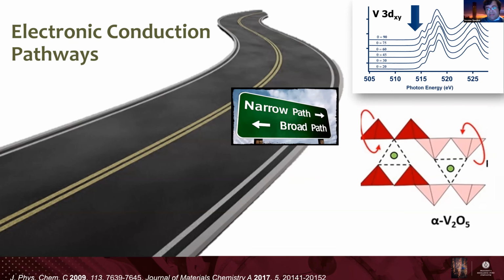This is the structural parameter. In terms of the electronic parameters, the square pyramidal coordination of vanadium is not ideal, because from crystal field splitting, it gives you the dxy state as the lowest lying state at the bottom of the conduction band, and this narrow split-off conduction band during early stages of lithiation serves to localize electrons. And so the electrons are not very mobile through this lattice, and this is also a challenge in the system.